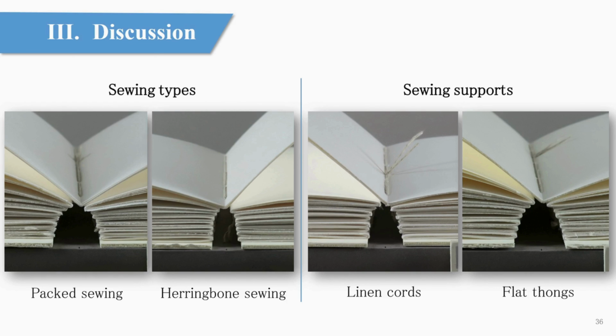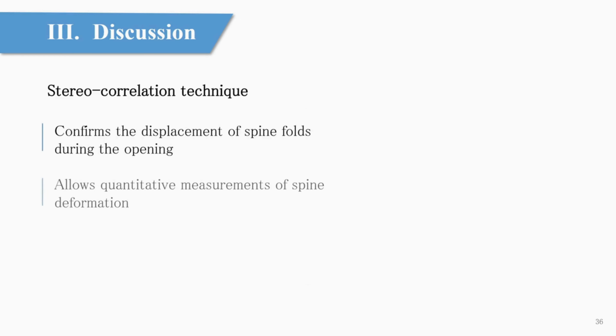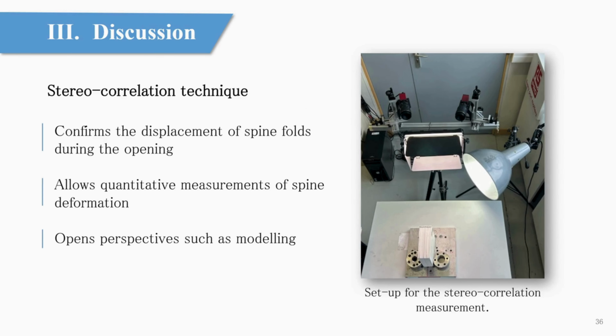Finally, the sewing thread is subjected to very little stress, and we did not observe any breakage or abrasion, despite the high number of test cycles, up to 86,400, on all the models. Finally, the measurement made by digital image correlation confirmed the observations reported in the literature. The deformation of the spine during opening is also created by displacement of the spine folds relative to each other, as suggested by Paul last year.